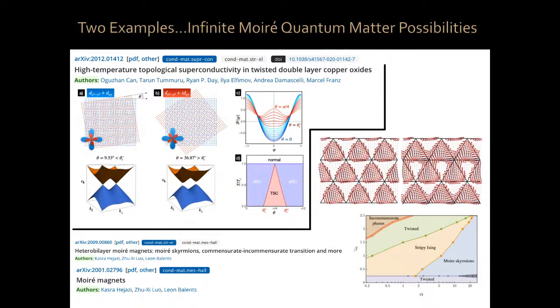Okay? So I'm showing here just two of them. So the group of Marcel Franz has predicted that if you stack two monolayer cuprate superconductors on top of each other above a certain angle, you will have a high-temperature topological superconductor. Okay? A very different type of superconductivity than is present in the cuprates. If you take two-dimensional magnets and you stack them on top of each other, you can create Moiré magnets, which have all different kinds of Moiré skyrmions and spin textures, etc., which you can also control. Okay? So there are plenty of things. These are just two examples.